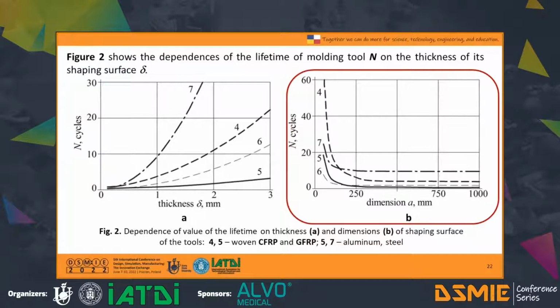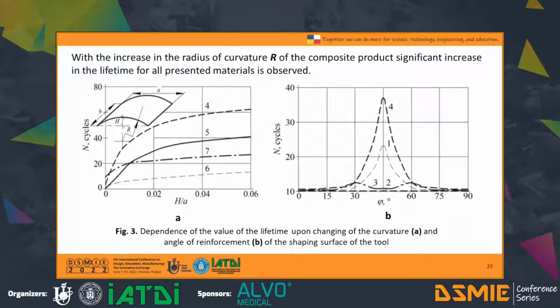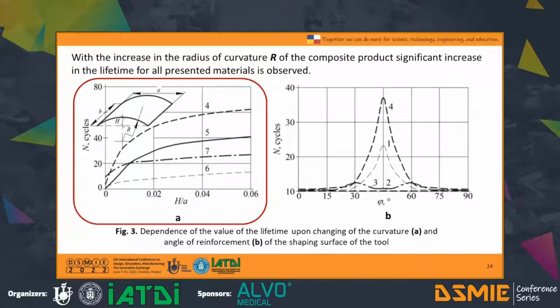However, when the dimensions of the molding tool are increased while maintaining the thickness of the shaping surface at the same physical and mechanical characteristics of the material of the shaping surface, its lifetime is decreasing rapidly. The value of the lifetime of the molding tool depends significantly on the special shape of the shaping surface. In figure 3a, it can be seen that with the increase of the radius of curvature R of the composite product, at least on one side, a significant increase in the lifetime for all presented materials is observed.